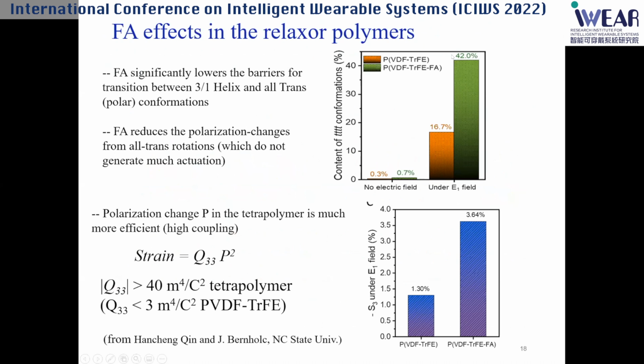And with FA, you can immediately raise it to 42%. And if you convert this into strain, for the pure PVDF TFE it's about 1.3%. And with FA, with only one—actually in the calculation there's only 1% more of FA—the strain can be about 3 times more. So this means with a very small amount of FA, the double bond, we can generate much higher electromechanical response, from the theoretical side proving what we have done experimentally.